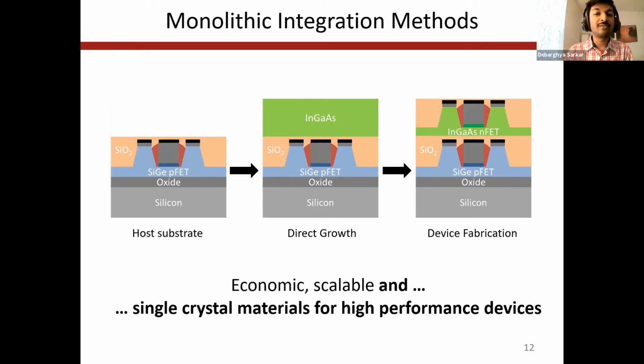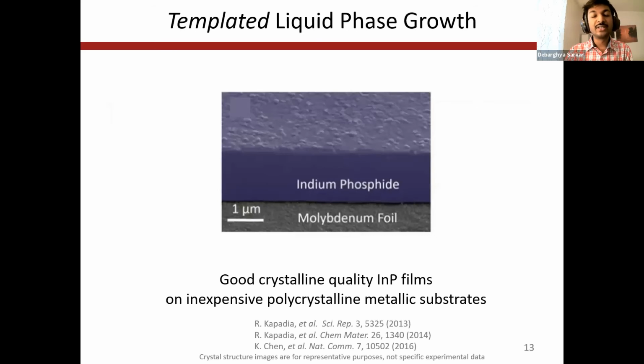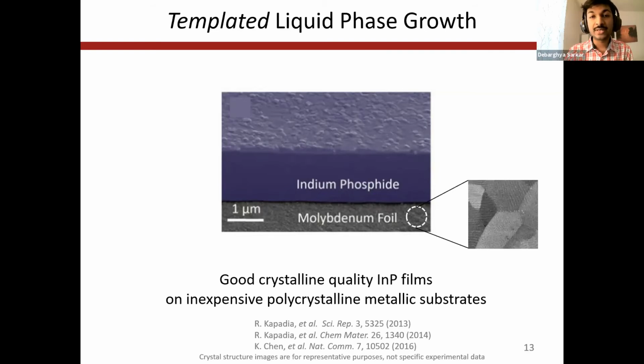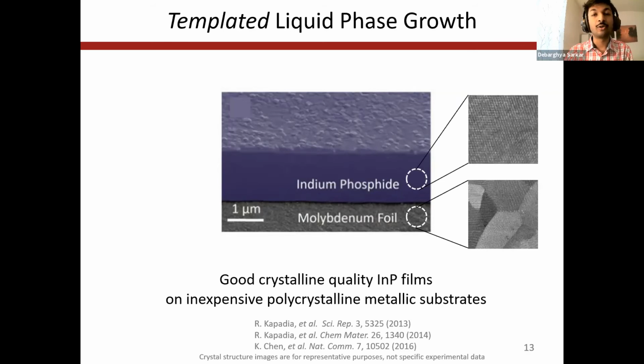So instead of working with the traditional vapor phase growth methods, we adapted this newly introduced growth technique called templated liquid phase growth, where it was demonstrated that indium phosphide films of good morphology and crystalline quality can be grown on inexpensive polycrystalline metallic substrates. In other words, even though the substrate is polycrystalline and unsuitable for electron transport, the material grown on top can be single crystalline and made usable for electron transport.